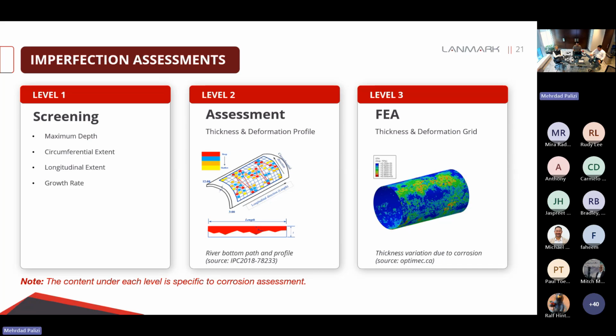So when we are doing imperfection assessment, we are generally using a three-level approach. Level one is screening. Here we are using fast, simple checks based on the feature dimension and operating data. It is basically for screening out low-risk features. Then we have level two assessment, which is going to be more detailed. Here we are using the elaborated data for our features. Let's say in the case of corrosion, we are using the thickness grids for the corroded area. In the case of the dent, we are using the deformation data, specifically the longitudinal and transverse profiles going through the peak of the dent.